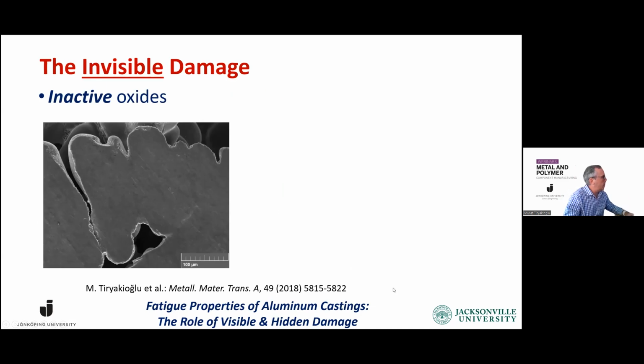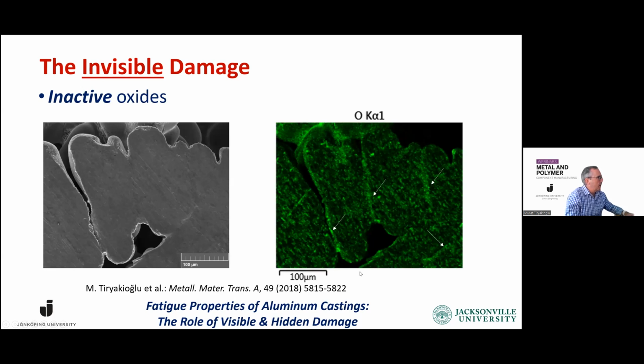Then we went to another place near this pore, and this looked like an interesting place. And when you look at it, there doesn't seem to be much other than the pore. The pore is always getting our attention. But again, turn on the X-ray map, and all of a sudden you see all these bifilms that are there that did not open up. They are just closed. They remain closed, although we did our best to open them up. So that is the invisible damage that we are referring to in today's webinar.